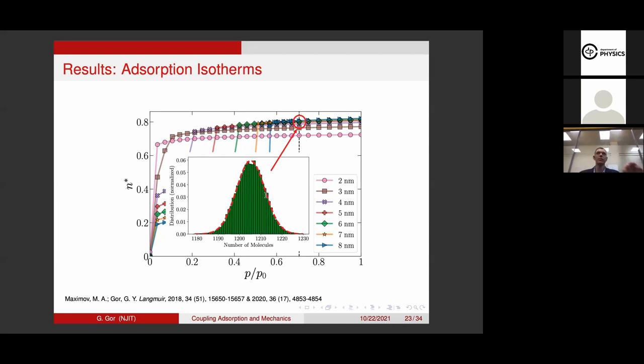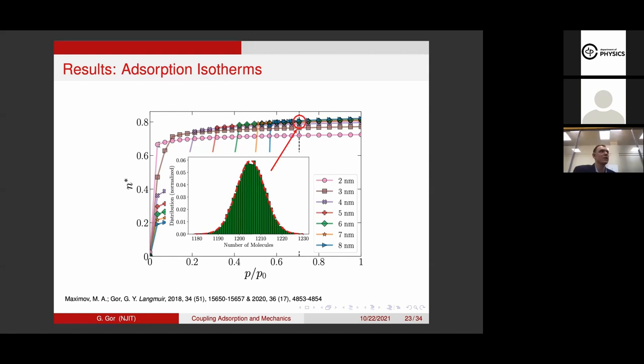Distribution where? Inside the pore. If you have an 8-nanometer pore, inside you could have around 1200 nitrogen molecules — it's a tiny molecule. For the smallest pores, roughly two nanometers would have about 50 molecules inside, so the statistics becomes much worse. Below two nanometers I'm not going to show any results because the distribution becomes non-Gaussian and we're not sure whether you can interpret these fluctuations in terms of compressibility.